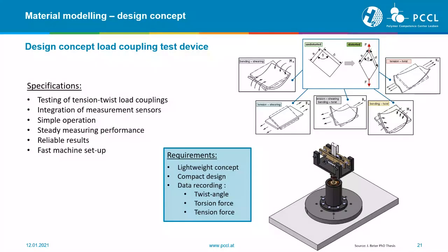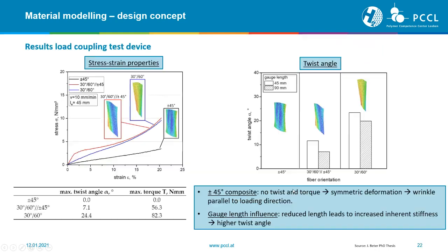And therefore, we've defined the design concept to measure these load coupling forces and moments by introducing a new load coupling test setup, directly recording the twist angle, the torsion force, and the tension force. And here we are with the first results of this test setup. On the left side, you see stress-strain properties. On the right side, you see the twist angle.